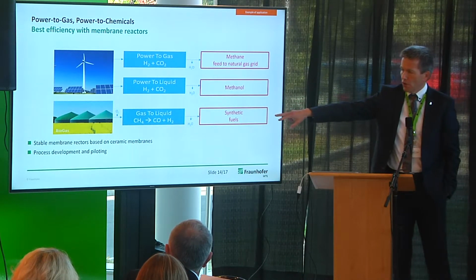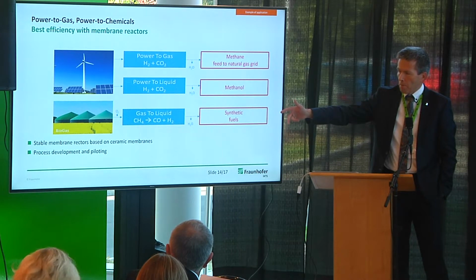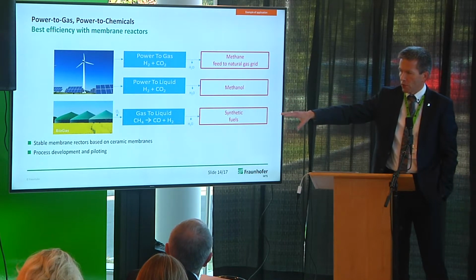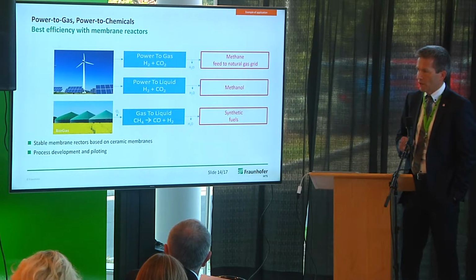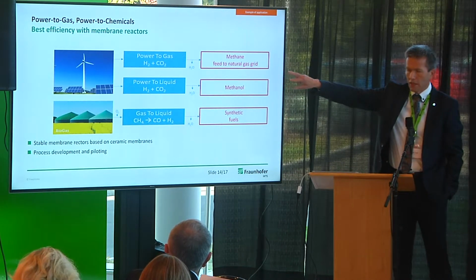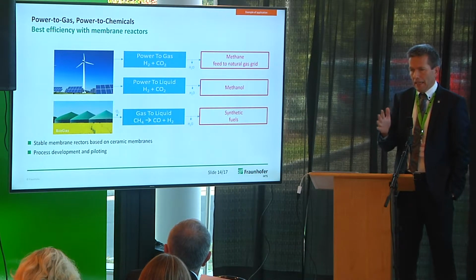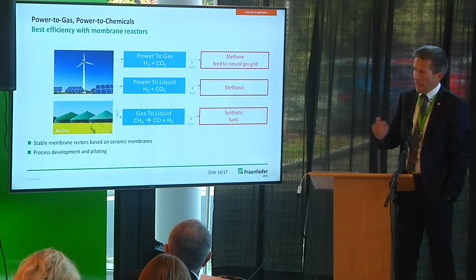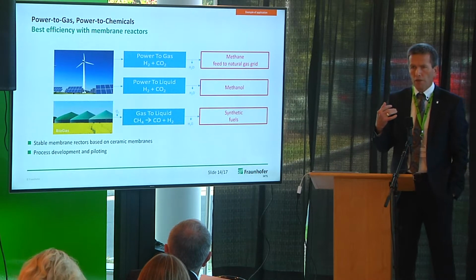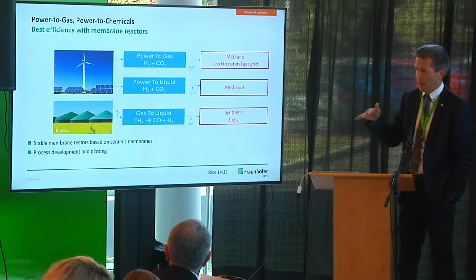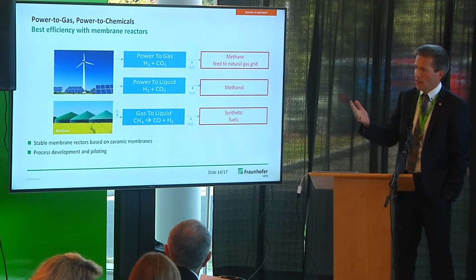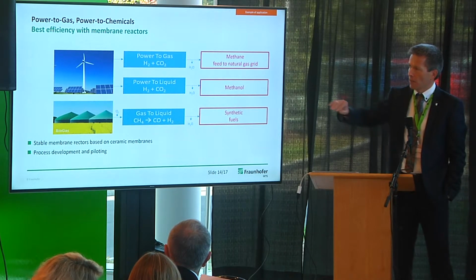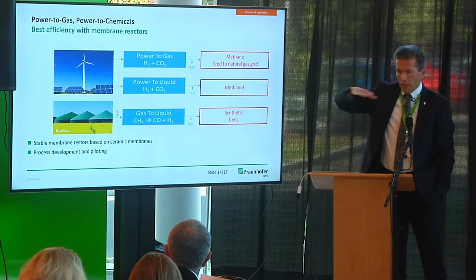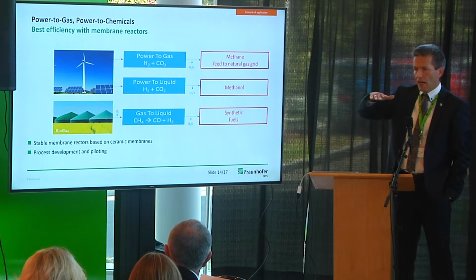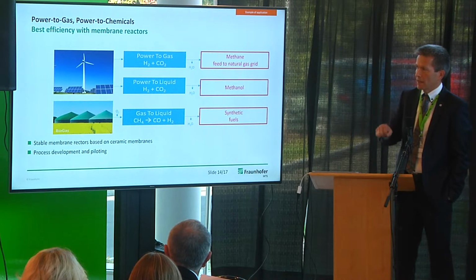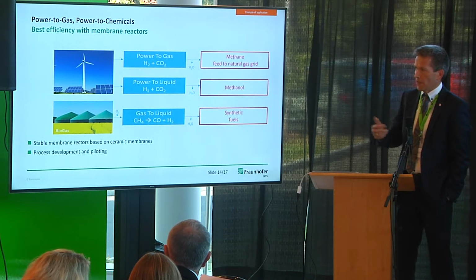And in the further transformation of the syngas to synthetic fuels, hydrogen is formed as well as in these previous two reactions. And so we have a limit in the equilibrium of the reaction. And our approach is to remove the water from the reaction and to shift the equilibrium to a higher yield. At the same time, the methane, you keep methane on the high temperature feed side,